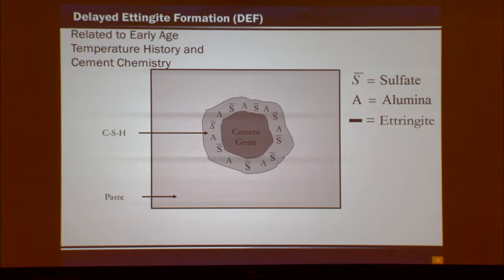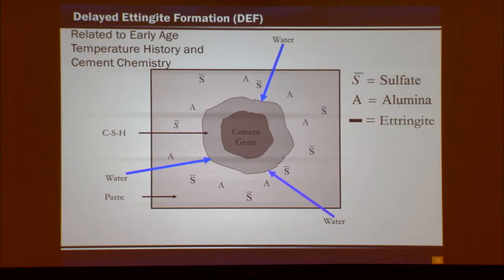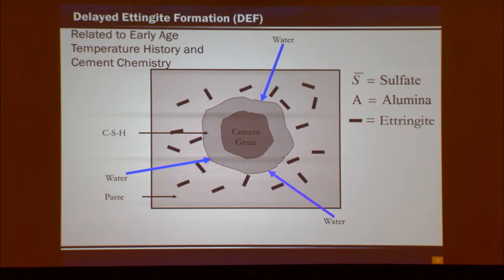Okay, no big deal. It didn't happen the way we wanted it to happen. Is that a problem? Well, in 10 years, it may be. Because as water comes into our concrete, because it's low permeability or whatever, these sulfates and aluminates get back into solution. They're like, hey, I want to go swimming, and they go into the pore solution. But they don't like being alone, so they have to find each other, and they make ettringite. Ettringite is a crystal that loves to grow big. And as this crystal grows and grows and grows, it exerts pressure. Concrete's not good in tension, and therefore we get cracking and substantial cracking.